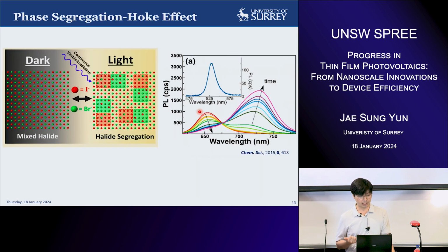So what happens in this wide band gap perovskite, if you put iodine and bromide in order to enlarge the band gap? So ideally, we can think about having a very nice mixture of the halides. That happens in dark, so iodine and bromides are just uniformly distributed under the dark. However, under the light illumination, these halide ions, they segregate. So there's iodine segregate regions and bromide segregate regions.